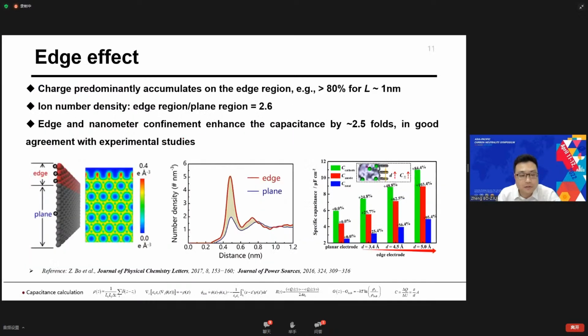So the second is the edge effect. Experimental studies have shown that the energy storage capacitance of graphene edges is much higher than that of the basal plane, about 2.5 times higher. This is the so-called edge effect.